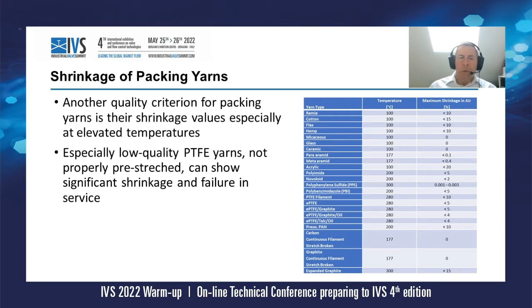Especially, for example, low-quality PTFE yarns, not properly pre-stretched, can show significant shrinkage and failure in service due to extrusion and related high gland pressure losses. But also with other materials which show high shrinkage, problems can occur and the service life will be shortened.